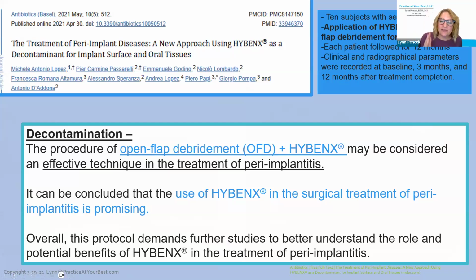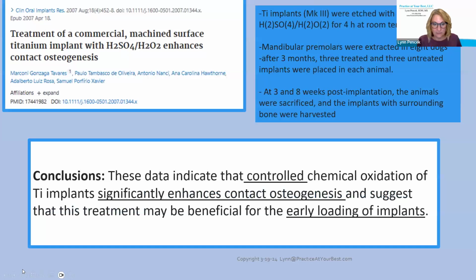So I don't see desiccation therapy as appropriate for management on a healthy patient or management for mucositis. I see this really more for peri-implantitis, and right now the research is more with open flap debridement. With these cases, we're getting excellent bone regrowth and bacterial reduction. The data is indicating that in controlled chemical oxidation, the titanium implants significantly enhance contact and osseogenesis. So if we're going to graft and try to regrow bone where there's been recession and threads exposed, this is very promising.